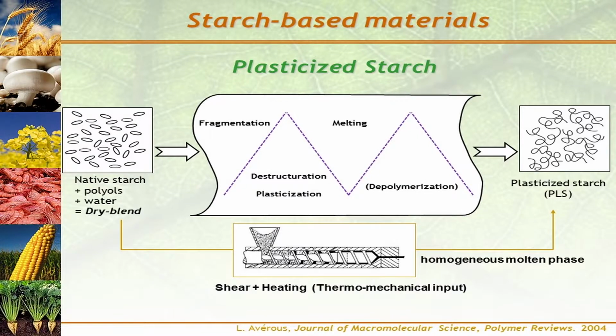So this is one of the processes that we have developed to obtain plasticized starch. The first step is a dry blend step, which is very similar to the dry blend process you have for plasticized PVC. That means we start with the native starch powder, add the non-volatile polyol plasticizer, typically glycerol, and then recover the dry blend that we put in a mixer, for instance an extruder, with some water, and with the shear and heating we have the fragmentation of the starch granules and its destructuration, plasticization, and hopefully we obtain an